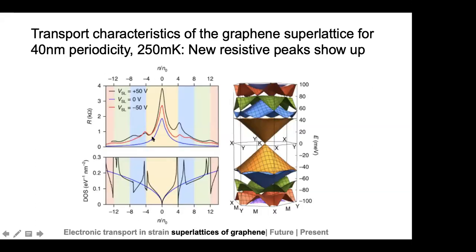So what you'll find is that on this top left panel, this blue curve corresponds to zero superlattice potential. You have the normal resistance peak at Dirac point. But if you increase the superlattice potential, if you change it to plus or minus 50 volts, these additional peaks show up in the transport characteristics. They also did DFT calculations to look at how the band structure will look under these superlattices, so under these potentials. And for plus 50 volts, this is sort of what the band structure looks like.